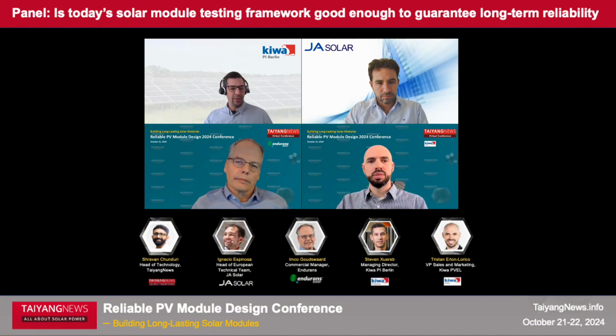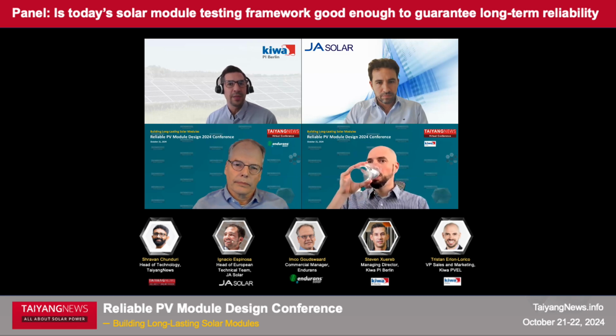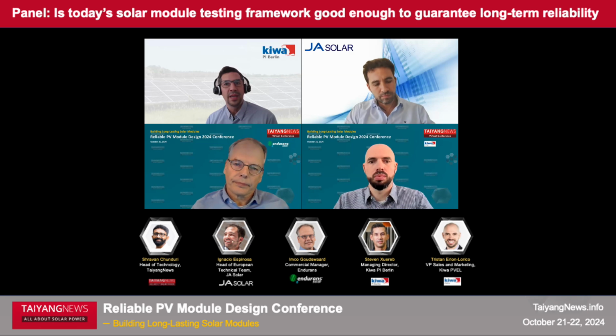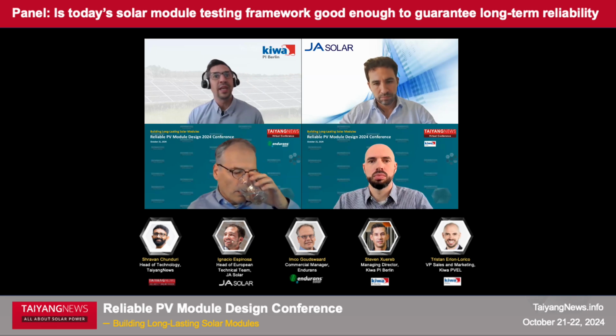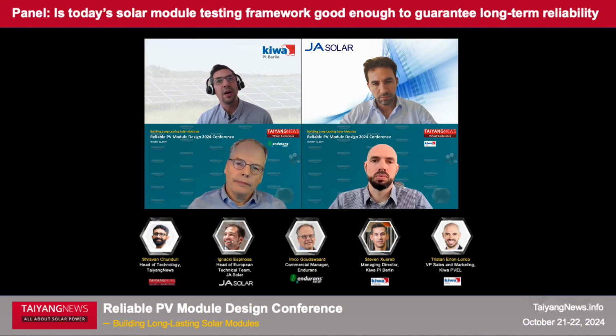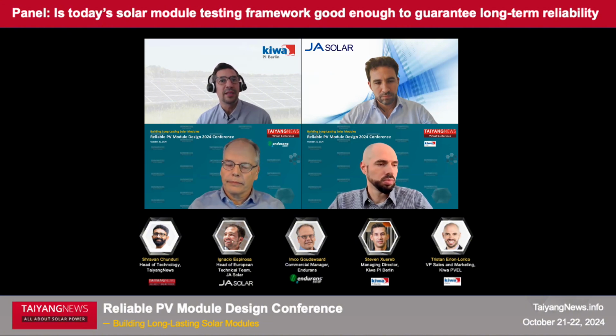No, I agree, and I think we've had a similar experience with our testing of TOPCon and our UV results. And just speaking to people in the industry as well, you hear, as Tristan said, there are different ways of going about optimizing TOPCon cell technology, and I think some cell manufacturers have gone in a direction of trying to optimize the cost-saving benefit and efficiency side of things. So maybe on the efficiency side, taking out UV blockers on the one hand, and on the other hand, with the passivation layer, trying to save costs by making it thinner and thinner. All this leads to a propensity of being more sensitive to UV, whereas others, perhaps the early adopters, were more conservative, and we didn't see this kind of sensitivity in the market yet.